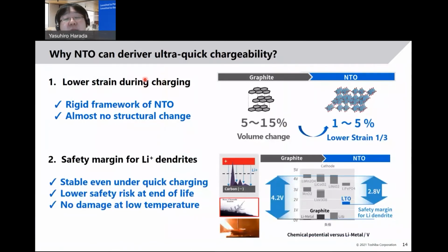As I explained in the background, ultra-quick chargeability with safety will be strongly required for the next generation batteries. We consider NTO battery can do that because NTO shows almost no structural change compared to the graphite. So NTO would be almost undamaged even under quick charging. Moreover, NTO has a safety margin against lithium dendrite formation.